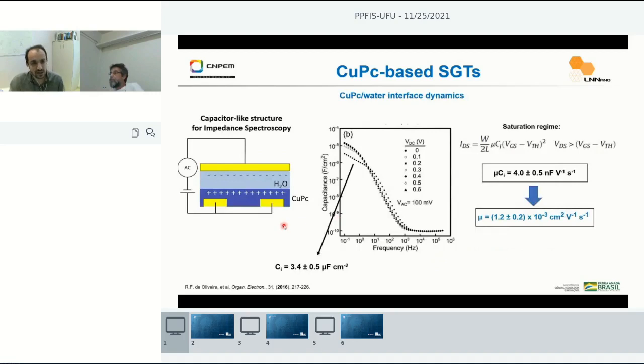With the same device, you can just change a bit the electrical configuration. So you can short circuit source and drain, okay? And use impedance spectroscopy to probe the capacitance at our device interfaces. So here we have a curve, which is the capacitance versus frequency obtained from electrical impedance spectroscopy.